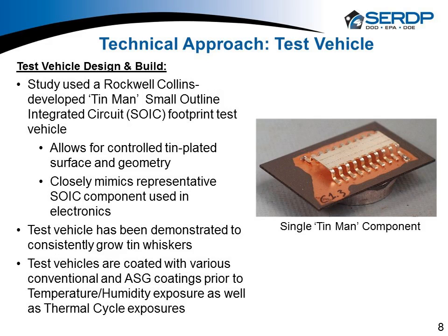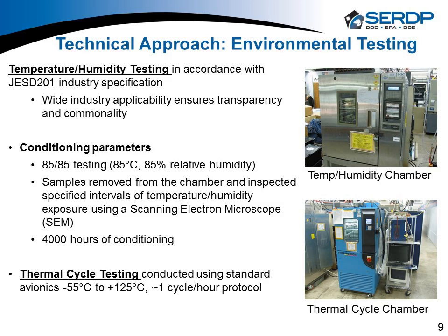So if I go to slide 9, what we chose for testing as far as our conditioning of this was two things. One was thermal cycling, and we did just a little bit of thermal cycling. Some of the review board members looked at that and said, it's a ceramic, and if we're going to take it through thermal cycle, thermal shock, we need to make sure that ceramic adheres and does what it's supposed to. So we did some standard industry thermal cycling in terms of what avionics sees, which is -55 to +125, about a 1 hour total cycle.